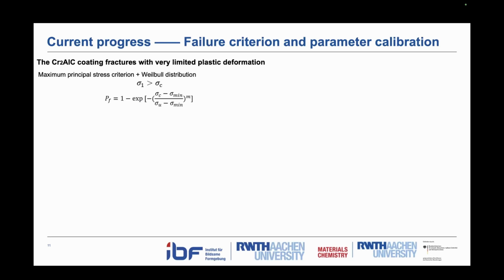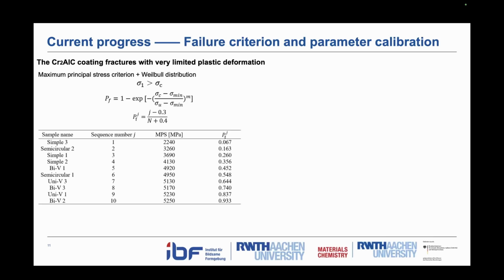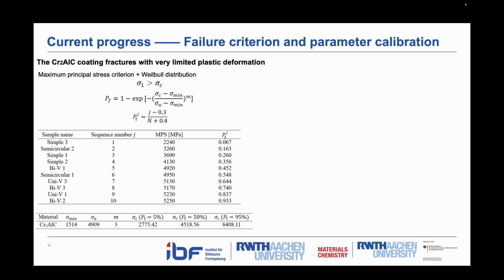And there are several parameters we need to calibrate. So what we do is that we calibrate the failure probability at the corresponding maximum principal stress that we have already sequenced from the smallest one to the highest one. Then we can calibrate the corresponding parameters. We also consider 3 failure probabilities, which refer to 5%, 50%, and 95%.